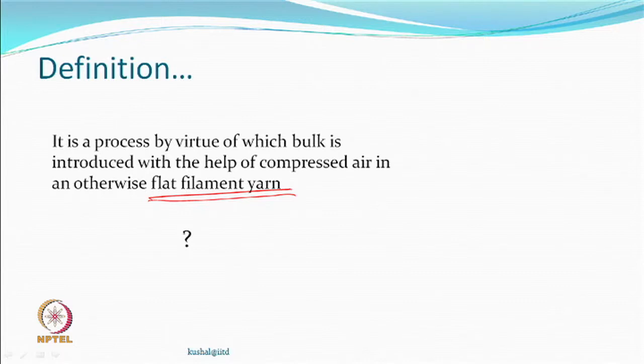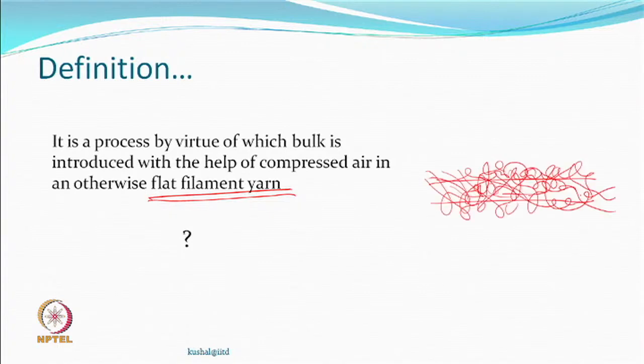What would that mean? Probably some kind of structure where there are loops, bends, and curls which get introduced because of deformation caused by the compressed air. There may be some areas which are denser and some which are lighter. We expect the compressive resilience to be high — you compress the loops, remove the force, and they expand back.